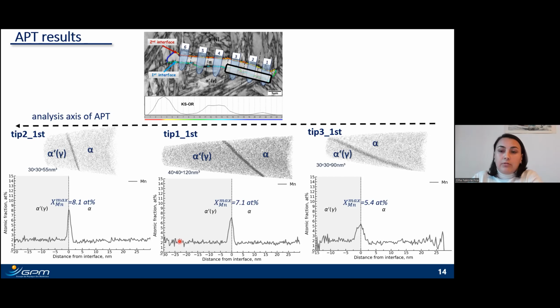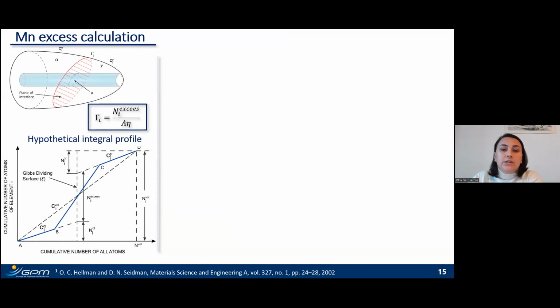Therefore, to quantify the manganese segregation at the interface, it is necessary to calculate the interfacial excess, known as Gibbsian interfacial excess, because it is independent of experimental conditions.